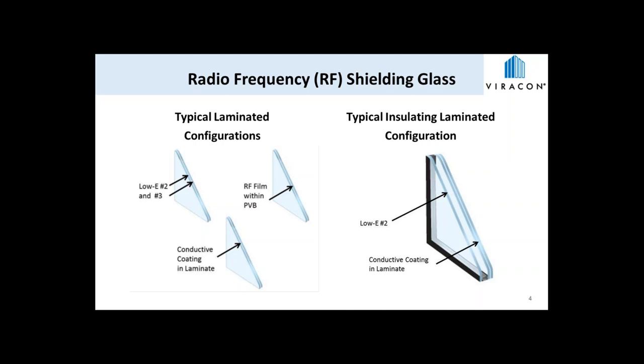A typical insulated laminating unit makeup takes the base laminate, typically the conductive coated laminate makeup due to its high optical transparency, and includes a low-E coating on the number two surface for aesthetics, thermal, and solar performance.